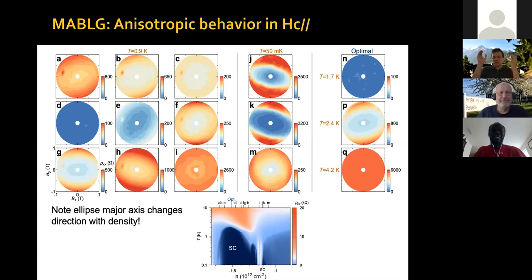So this is not spontaneous symmetry breaking, but has to do with a very strong strain, and of course you have a response which is symmetric with respect to the strain axis, okay? But of course, strain is not going to depend, for a given sample, on how many electrons we put in the sample over very small density changes of electrons. So the fact that the major axis of the ellipse is rotating with density indicates that it is very likely of electronic origin. This is not something associated with a very strong strain that is spinning the direction of the ellipse.